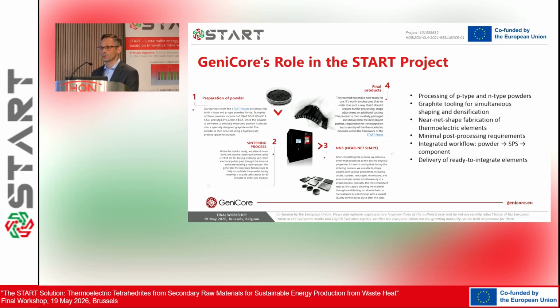A lot of different compositions that Alvise presented were developed, and there is, unfortunately, no one way to sinter any type of material, and even a small deviation in the composition of the powder generates some problems for MBN, and the same in GeniCore's case, because with the delivery of each new batch we have to redefine the sintering parameters to achieve the same properties.